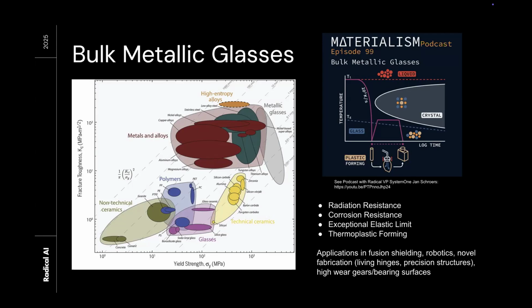The other thing that is really, really exciting about bulk metallic glasses as an application is this ability to do thermoplastic forming. With a glass, you have two key temperatures. You have a glass transition temperature where your material starts to soften, and then you have this recrystallization temperature where you might start to nucleate new phases. If you can design a material that suppresses the recrystallization temperature, then you can cast a glass, heat the glass up to the point where it is processable with thermoplastic methods developed for conventional plastics, and make incredibly intricate parts with bulk metallic glass.